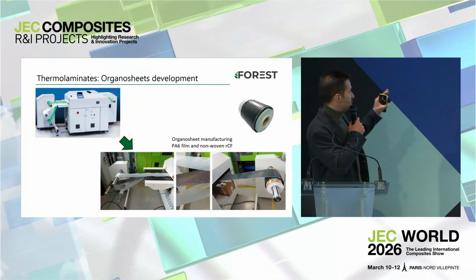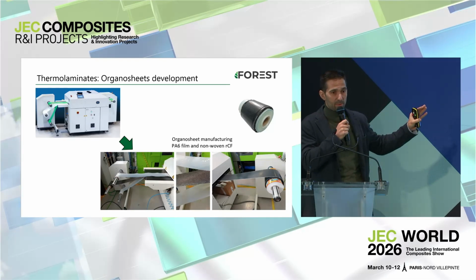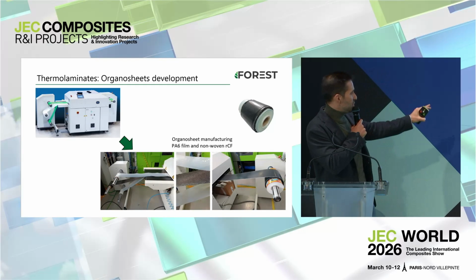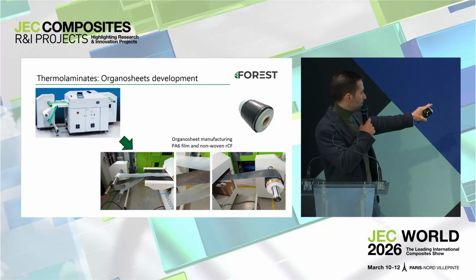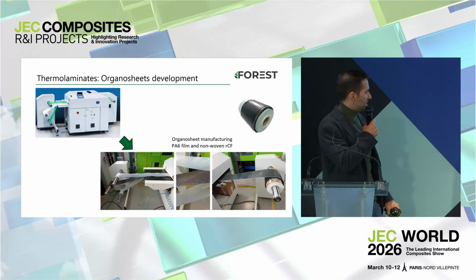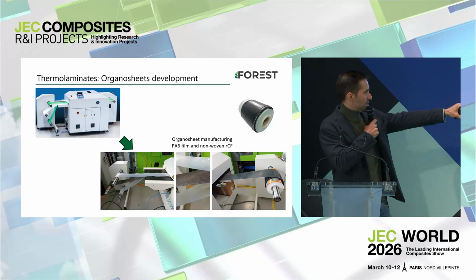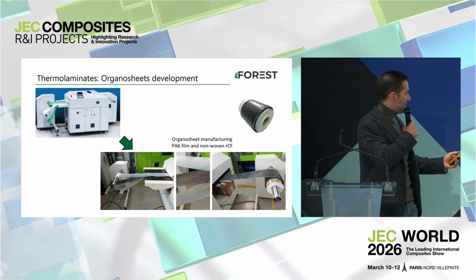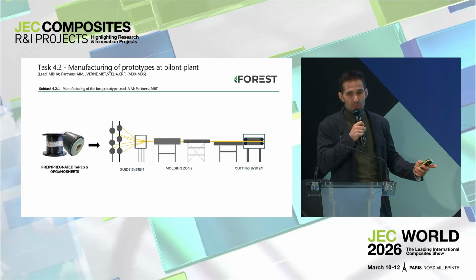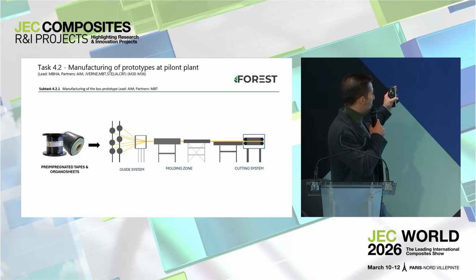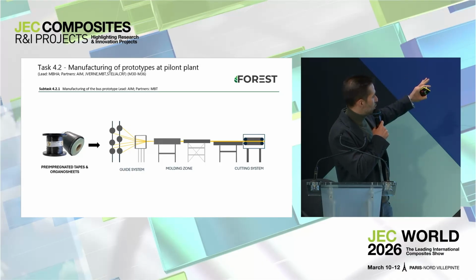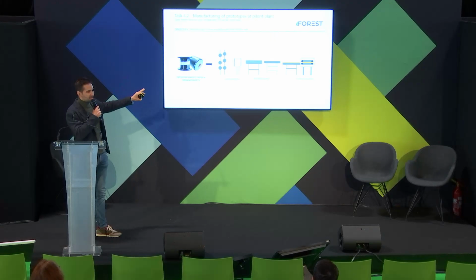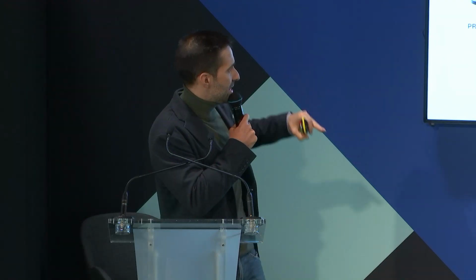For these organosheets, we use a commercial thermolaminating equipment in which we sandwich the non-woven carbon fiber between two layers of polyamide 6. Applying pressure and temperature, we obtain this organosheet. It's a pre-consolidated organosheet. Afterwards, we combine these two items, the UD tape on one side and the organosheet. We lay them up, or sort them out in a creel with a guiding system. All these tapes and the organosheet are guided through this system towards the pultrusion mold.